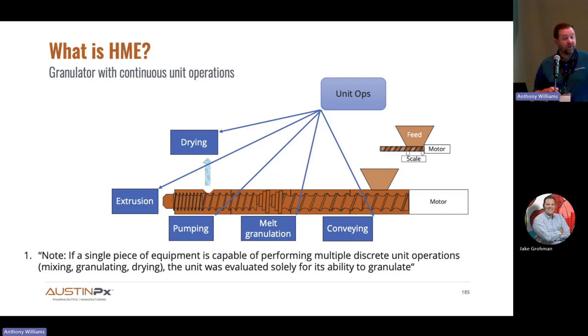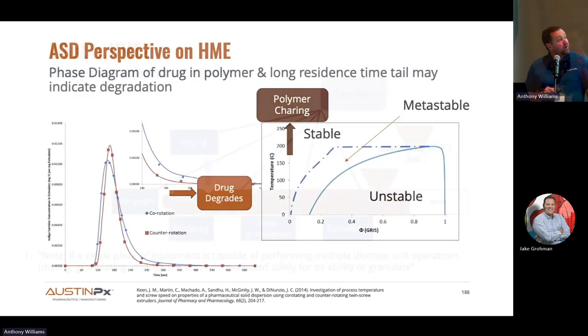It's also a pump. There's a vent. This is a very important process. If you don't control moisture removal or residual solvents from an extrusion process, the whole system can go haywire. And then, the term extrusion comes from this last little inch of the machine, maybe half inch. But melt extrusion is a good comparator for KinetiSol because they're both fusion-based ASD forming machines.